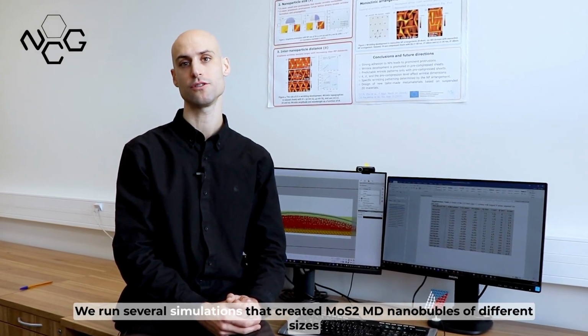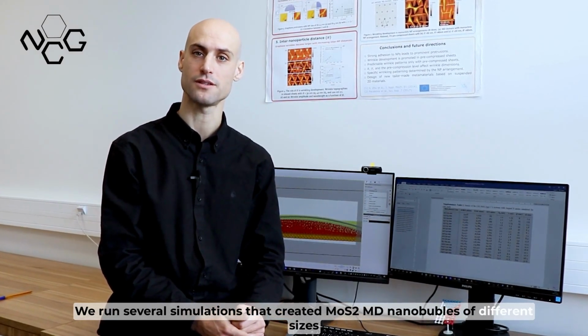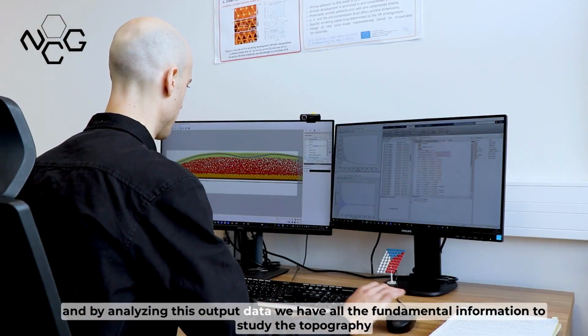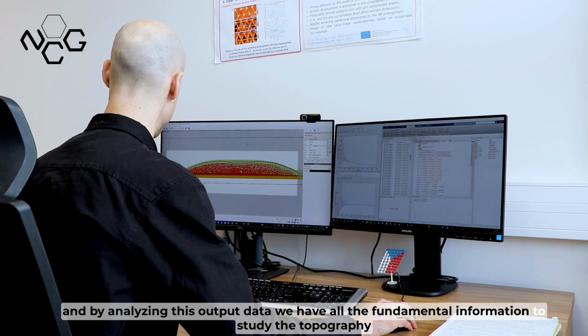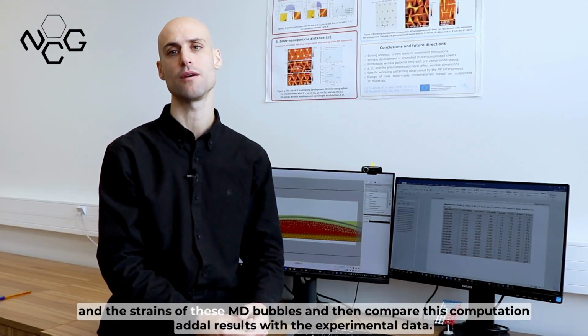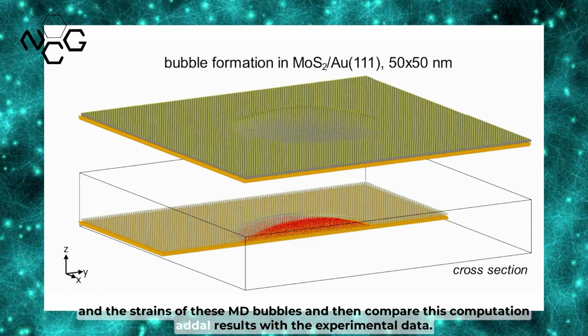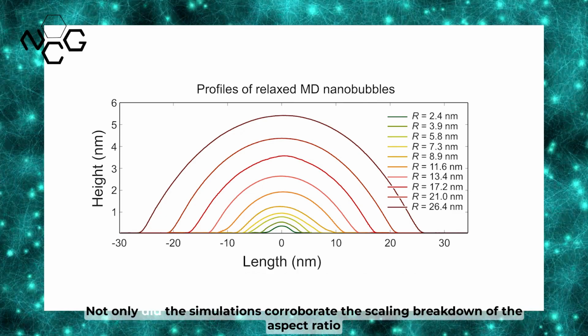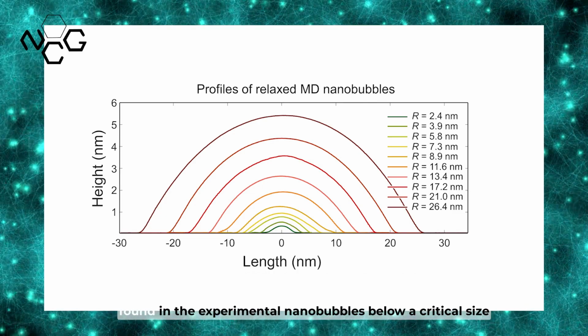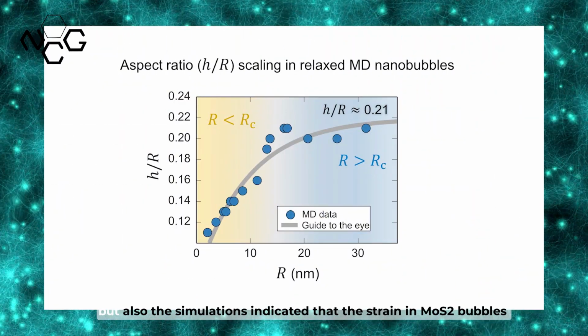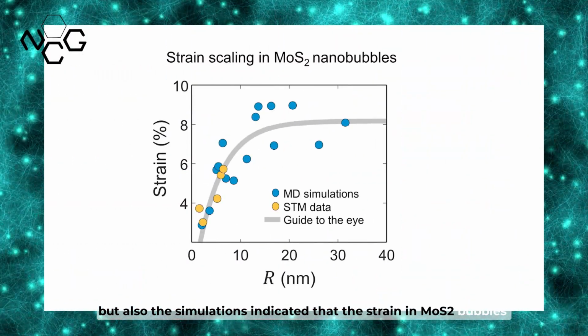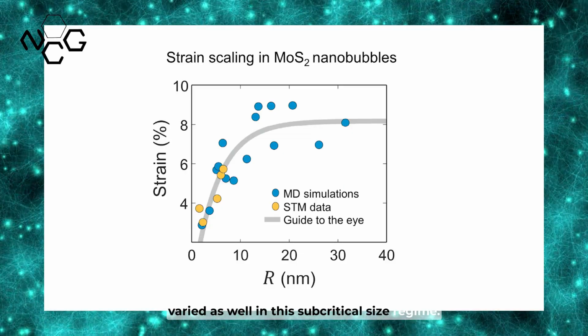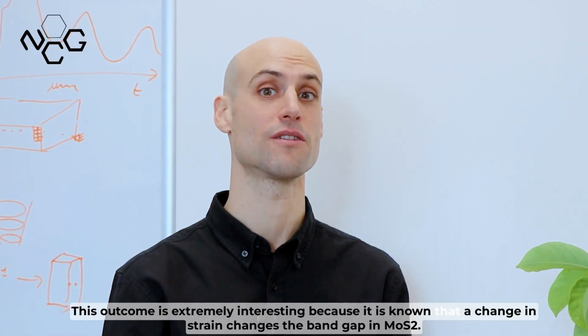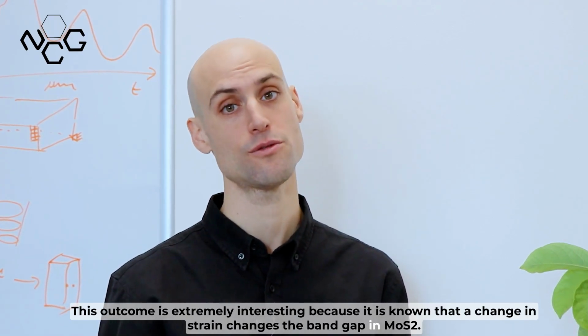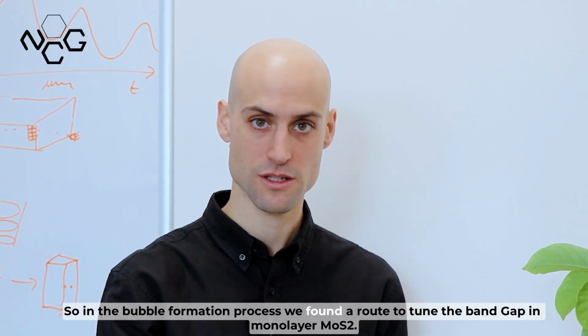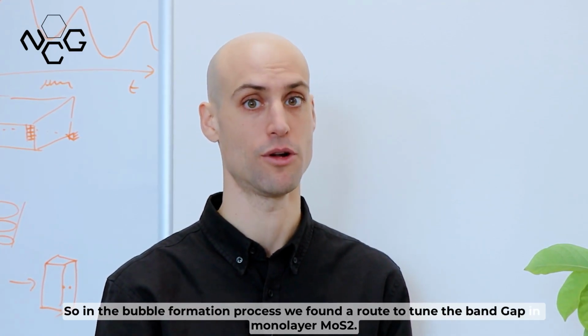We ran several simulations that created MoS2 MD nanobubbles of different sizes, and by analyzing this output data, we have all the fundamental information to study the topography and the strains of these MD bubbles, and then compare these computational results with the experimental data. Not only did the simulations corroborate the scaling breakdown of the aspect ratio found in the experimental nanobubbles below a critical size, but also the simulations indicated that the strain in MoS2 bubbles varied as well in this subcritical size regime. This outcome is extremely interesting because it is known that a change in strain changes the bandgap in MoS2. So in the bubble formation process, we found a route to tune the bandgap in monolayer MoS2.